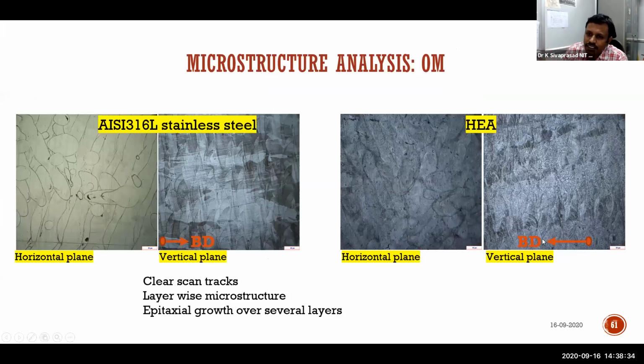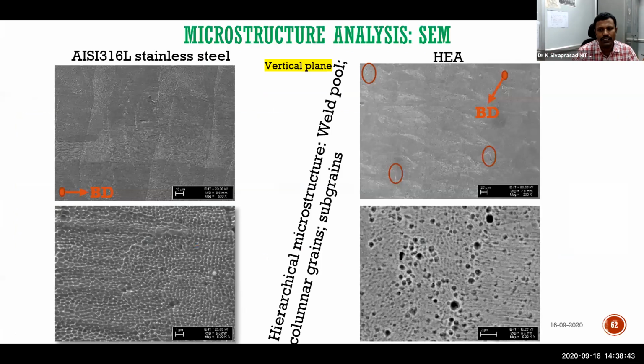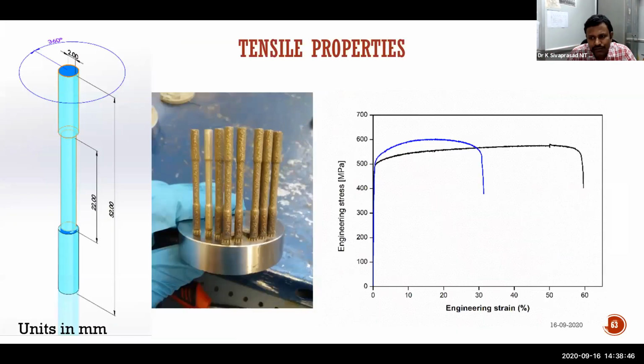In the microstructures, you can see that porosity was reduced to less than 1%, which is a challenging thing to do in additive manufacturing, but once it is optimized, it is nothing. You can do it comfortably. Then for doing tensile test, there is no standard yet completely evolved for tensile testing of additive manufacturing components. So we decided, as suggested by previous publications, the component was built in the form of a tensile sample and slightly polished, and we have tested that. You could see very high strength and very good ductility combinations, 30 plus percent ductility, which is uncommon for any kind of additive manufacturing components because porosity is reduced.